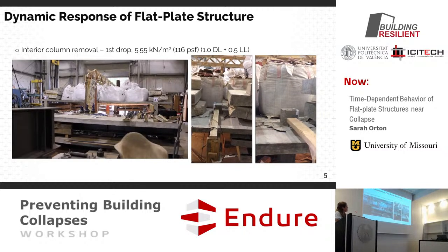And I had them all timed at the same time almost. So this deflected and the neighboring columns punched. And so the columns that were to the side, front and back, they all experienced punching shear failure. But the post-punching response, the post-punching capacity, was enough to stop the complete collapse. I think if I had just a little more weight, it would have gone completely through. A little bit less, I wouldn't have had punching failures. So it's like this little sweet spot right there.